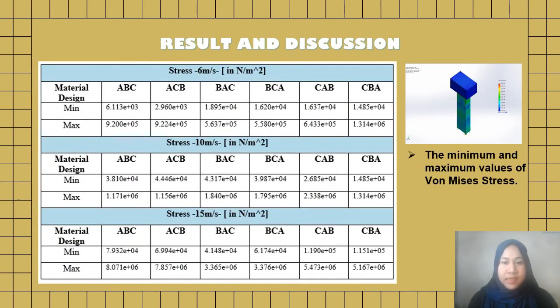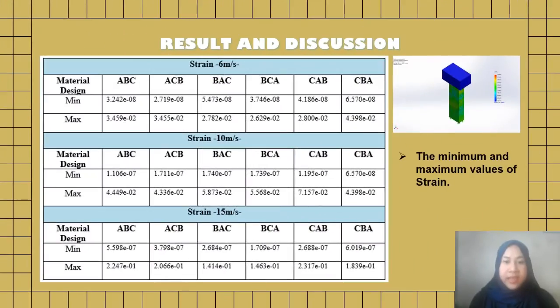As we can see, the minimum and maximum values of Von Mises stress for material design CBA are the same when it is impacted at velocity 6 meters per second and 10 meters per second. And then this table shows the minimum and maximum values of strain. All the data is obtained from the simulation results.